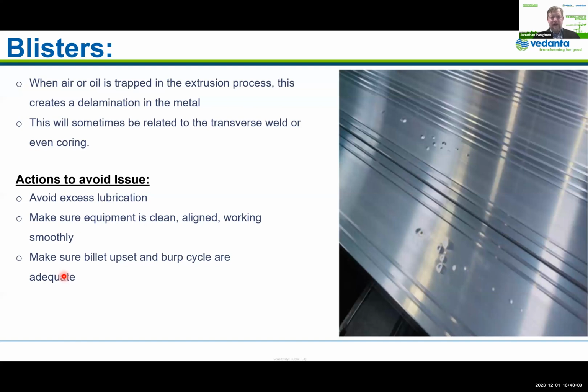These, of course, are air, possibly oil, that is in the process, and when the pressure of the die is released on exit, you very often can hear these blisters pop out. We'd audibly hear that there are blisters forming, and then you look and you see them. But it's basically controlling what's going into the container. If anything goes into the container, of course, it has to come out at some point. And for air, for example, every time you're loading a billet, you're also putting air in there because the billet is not a tight fit.